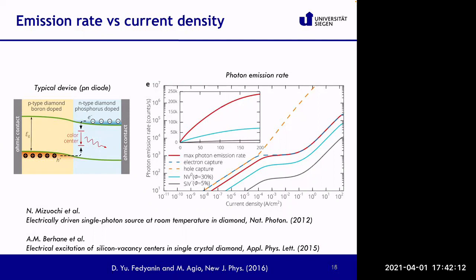So you see that the emission rate is strongly dependent on the current density that you have at the PIN diode. And the photon emission rate very much depends on the electron and hole capture process. So you see that, for example, the electron capture process appears to be the limiting factor, because you see that as you increase the current density, at some point, the emission process becomes quite flat until you go to such high current density that you activate other conduction processes, and therefore you get again enough electrons to provide holes and electrons for the recombination.